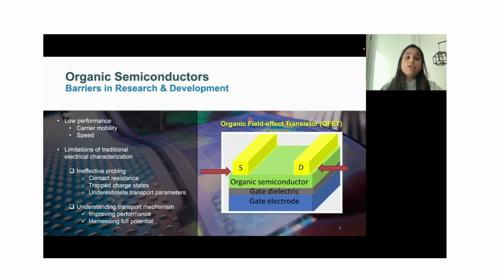There are certain limitations found in the traditional IV or electrical characterization of such devices, where the cause of ineffective probing often leads from high contact resistance at the non-ohmic contacts between the metallic contacts and the organic semiconductor found in these materials, as well as a higher density of trapped charge states both in the bulk and interface of these materials, which leads us to underestimate the transport parameters or transport properties of such devices.